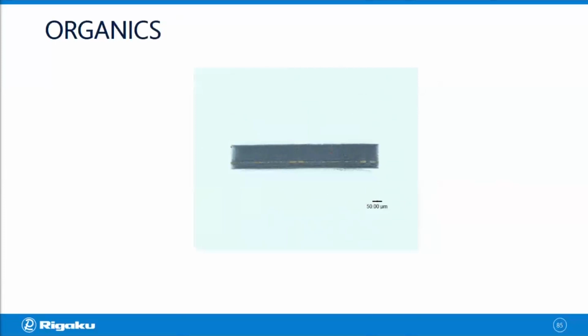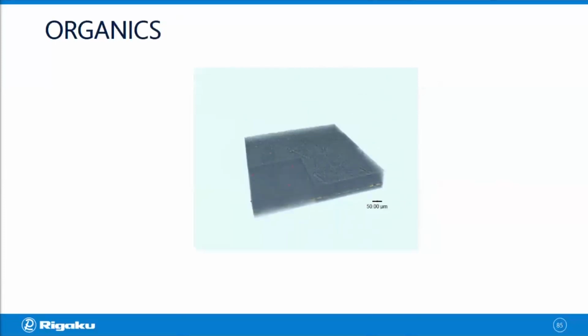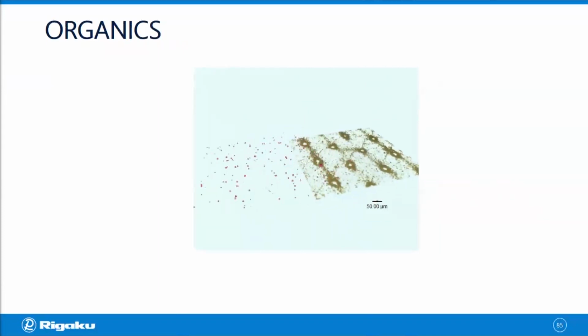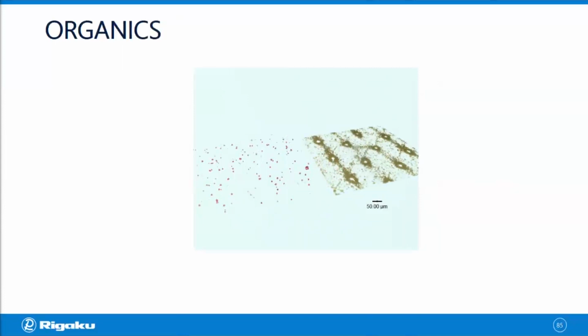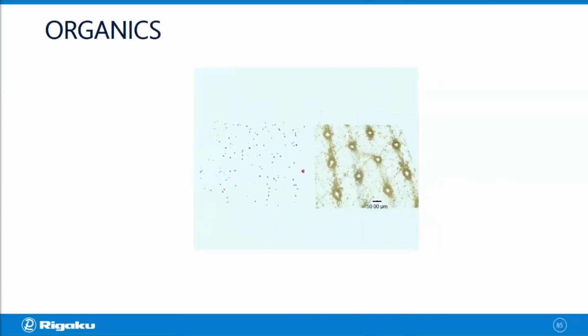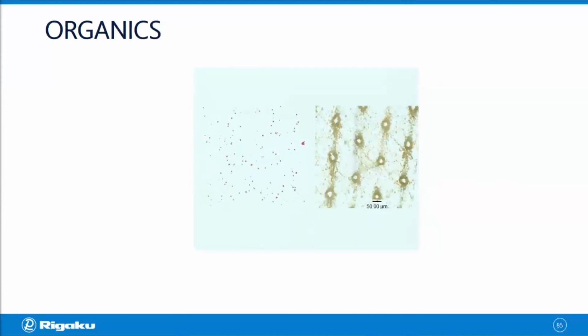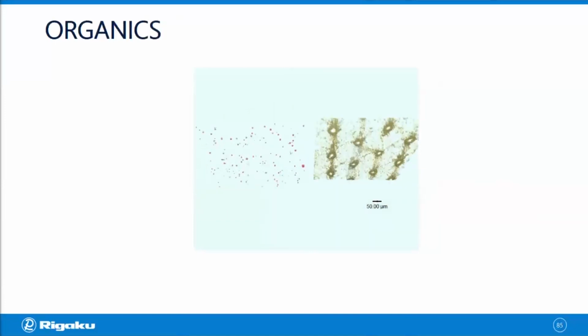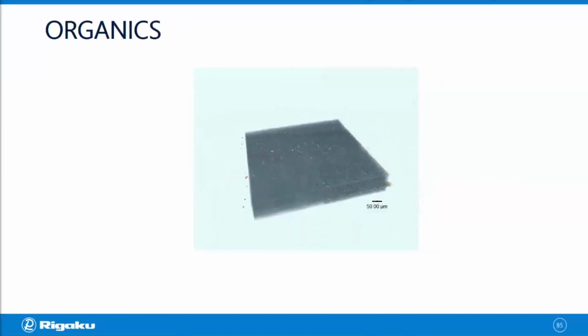This one is from a very thin organic film. The total film thickness is about 80 microns. And it has a membrane filter inside, which has a very small density contrast compared to the matrix. But you can image those filters and organic membrane filters very clearly by using low energy X-rays. This one was a scan with 5.4 keV X-rays.